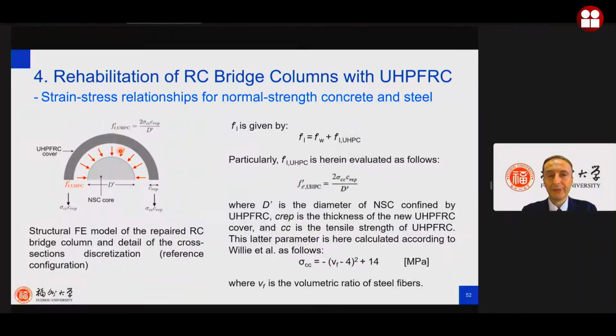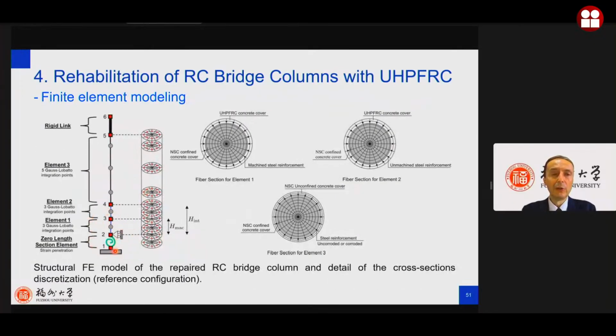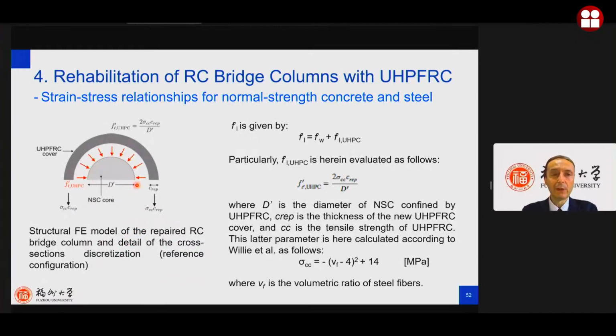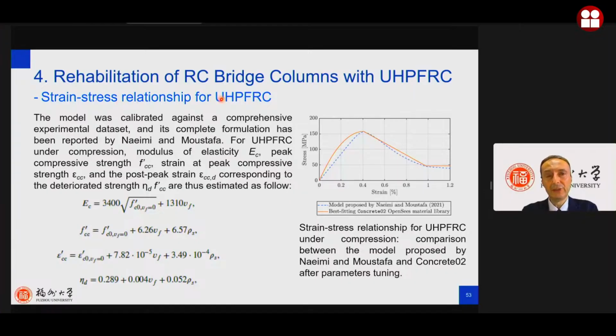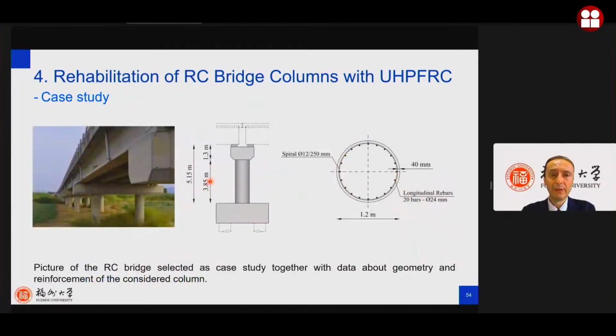For the concrete, we consider two different situations because, of course, where you are going to rehabilitate the bridge, the normal concrete in the core is in some way confined by the new ultra high performance fiber reinforced concrete cover. So we considered this effect. And we also considered the stress-strain relation for ultra-high performance concrete using the Naeimi and Moustafa law. So we calibrated adequately the concrete OpenSees material that we use. If you are using OpenSees, probably you use this kind of element. So we calibrated to follow this law proposed in the literature. Actually, we did many tests on ultra-high performance concrete and we developed our own three-linear model, but at that time, we used the one in the literature.